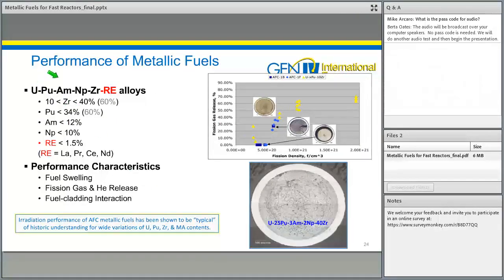What I mean by that is we've tested this base metal fuel alloy, so uranium, plutonium, americium, neptunium, zirconium, and then potentially with rare earths added to simulate recycle carryover. We've tested zirconium between 10 and 40%, plutonium up to almost 35%, americium and neptunium up to 10% or more, as much as 1.5% rare earth carryover. And even with these big changes in composition to the fuel, the performance characteristics, whether it be fuel swelling, fission gas release, fuel cladding interaction, tends to be what we call typical. We say metallic fuel behaves like metallic fuel, with very consistent performance, irrespective of some pretty big changes in composition.